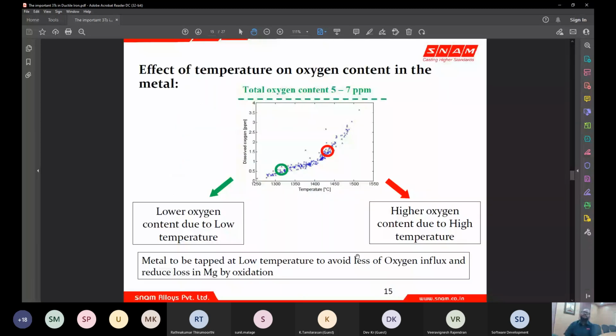So this is the effect of temperature on oxygen content. When you keep increasing your temperature, there is a high tendency that oxygen can get retained in your liquid metal for a longer time. And because of this high oxygen content, you start losing your magnesium and all the oxide forming elements in the form of oxides. And it should be lower, or at an adequate level. So it is better to tap at the lowest possible temperature, such that your oxygen influx or oxygen retention in your liquid metal is maintained, and the amount of oxides formed or loss of magnesium due to oxidation can be controlled.